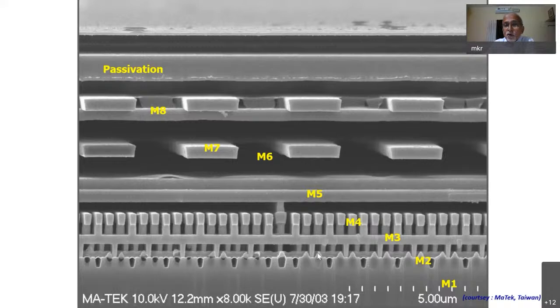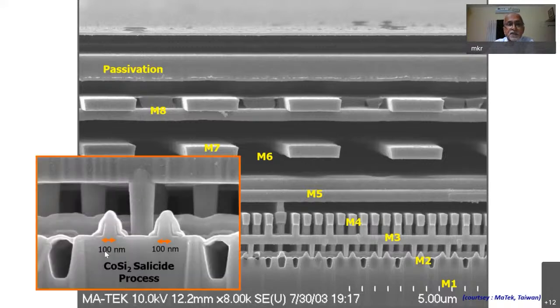If you see here, you can see small domes, which are the transistors. I'll expand it. This particular thing, if you expand, is one transistor. This is another transistor, two transistors. It is called a cobalt silicide process. When we have the transistor, there is an area here, either source or drain, which is silicon, so it's not fully conducting. It is only semiconducting, so it needs to be a high conductor. For high conductivity, we put cobalt silicide or tantalum silicide or something like that, a thin layer to make it conducting. That is why it is called a cobalt silicide process.